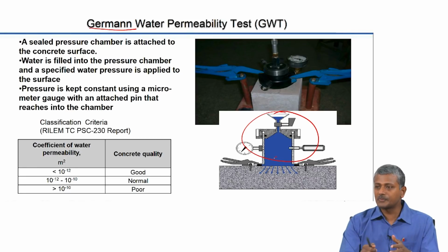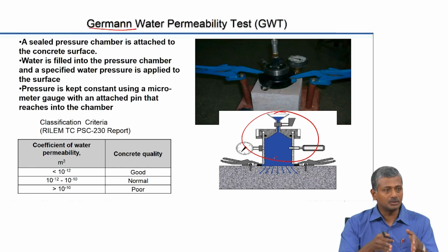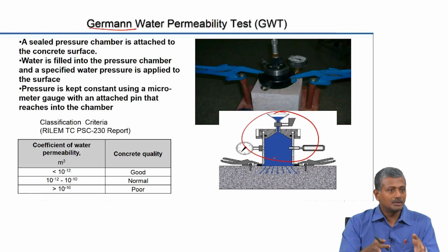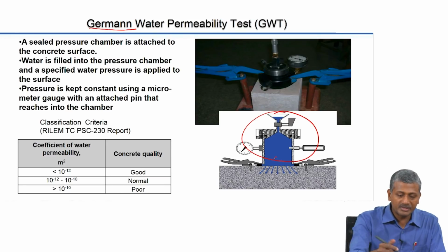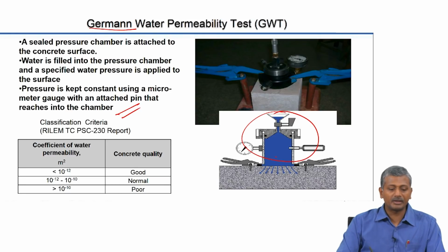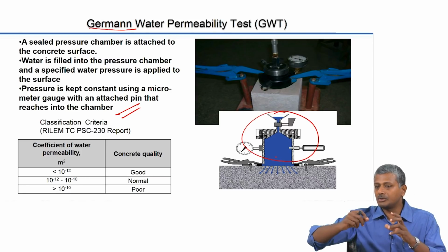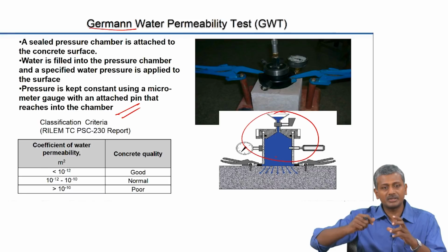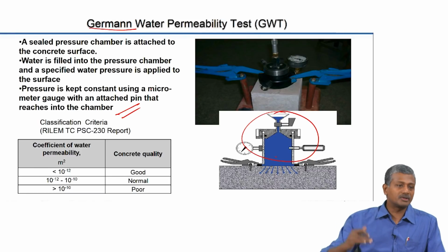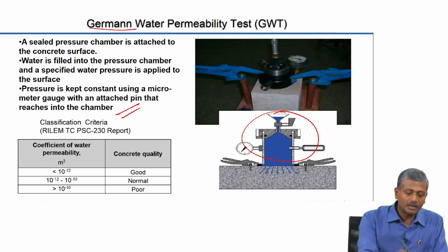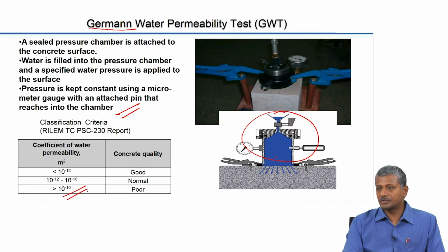Okay, so, the principle is the same. You are still applying pressure to the water to get it into the concrete. But the advantage here is that you can carry this to any real structure and do the test. Okay. So, pressure is kept constant using a micrometer gauge with an attached pin that reaches into the chamber. The amount of adjustment that you need to give for the pressure to remain constant is then converted to the amount of water that is penetrating into the system. And ultimately, you get again a water permeability coefficient from this test.